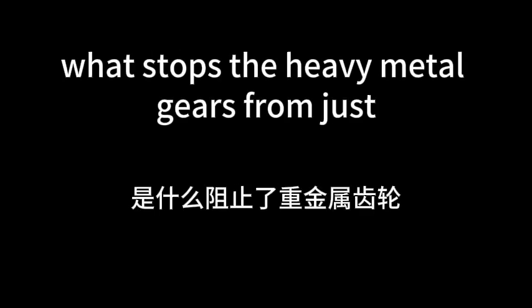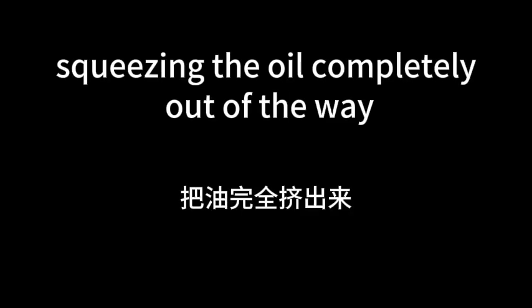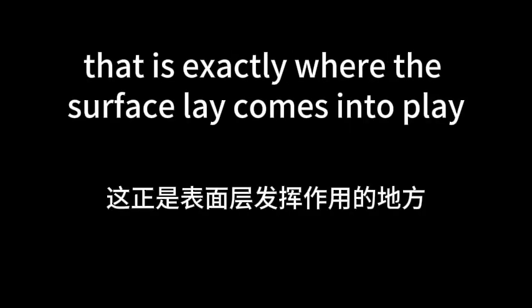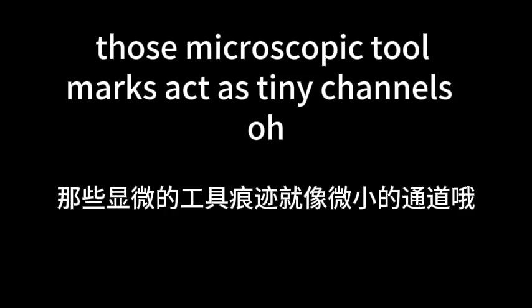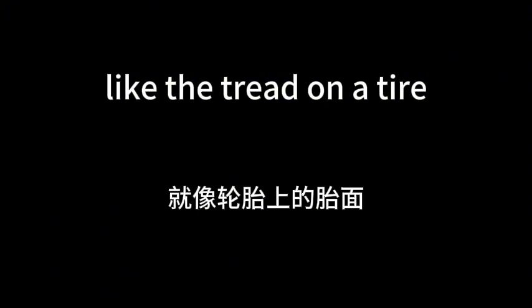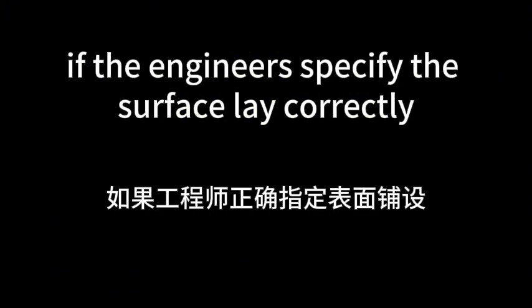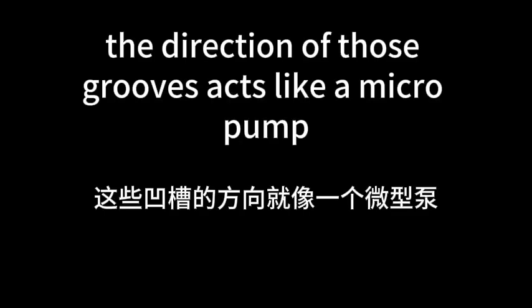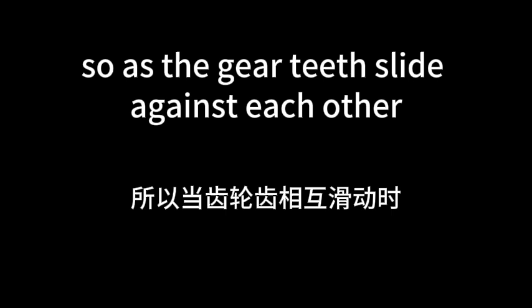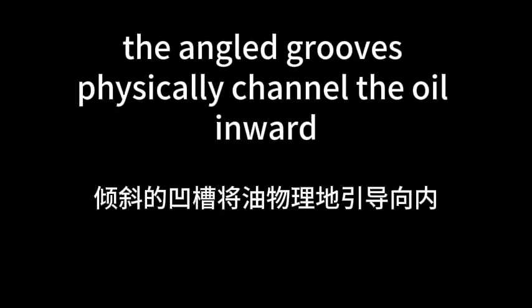But if the pressure is that extreme, what stops the heavy metal gears from just squeezing the oil completely out of the way? That is exactly where the surface lay comes into play. Those microscopic tool marks act as tiny channels. Oh, like the tread on a tire. That's a perfect analogy, yeah. If the engineers specify the surface lay correctly, the direction of those grooves acts like a micropump. So as the gear teeth slide against each other, the angled grooves physically channel the oil inward. Yes, actively trapping it in the high-pressure contact zone and maintaining that protective film.